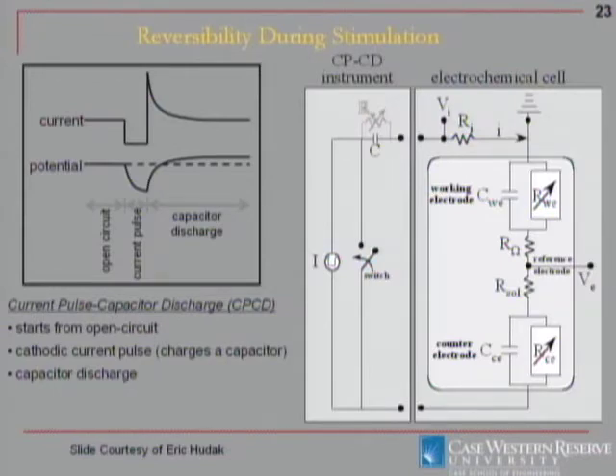So what we have here is basically we charge up a capacitor and then we close a switch to discharge the capacitor. And that's shown here. And the amount of charge that gets discharged should be, of course, equivalent to what you put into it. So it does imitate the idea of a balanced charge pulse. The other thing about this instrument that is good is we can monitor the potential of the electrode. And thus we can see within that potential window, that fingerprint of electrochemical activity, where our electrode could be sitting and thus what could be chemically happening at our electrode.